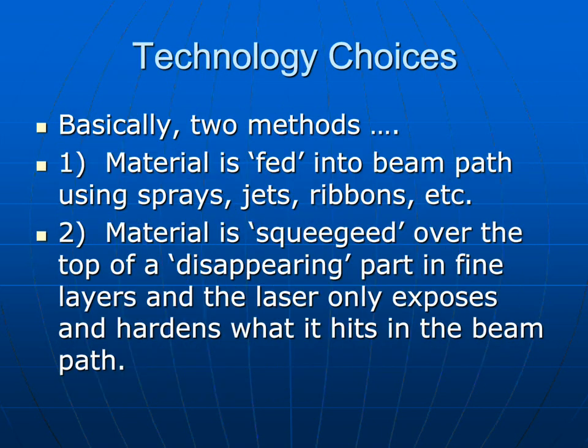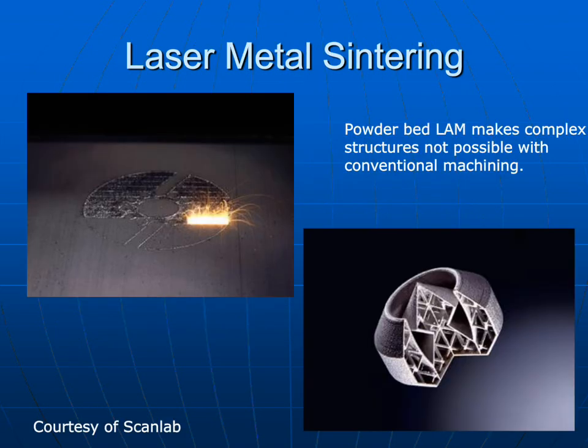So there's essentially two technology choices. In the one, you feed some material into the beam path, either using a spray, a jet, a ribbon, or whatever, and that's deposited on the part. In the second one, you have a part and you squeegee a layer of material, and then you do your laser processing, and then you lower the material, squeegee another layer, do the laser processing, lower the material, squeegee another layer, and you do this in fine layers, and then the laser only exposes and hardens what it hits in the beam path. So if you look at the upper right, you'll see the laser actually exposing and sintering some metal on a powder bed. And if you look on the lower right, you'll see the finished part, basically. And the finished part has all kinds of little internal chambers and things that you could never make with any other kind of machining process. So you're able to do things you can't do in any other way using 3D manufacturing.